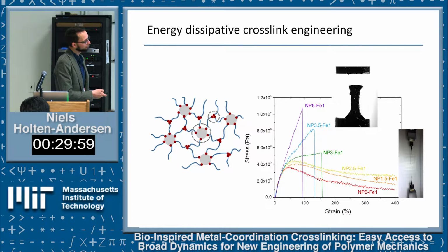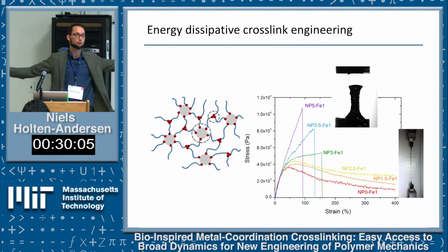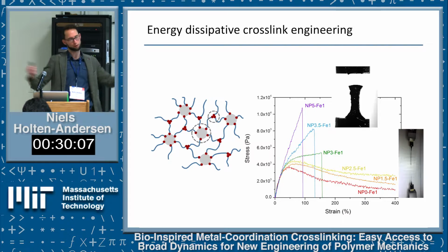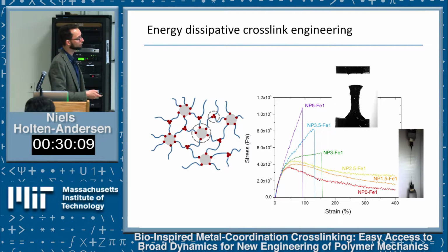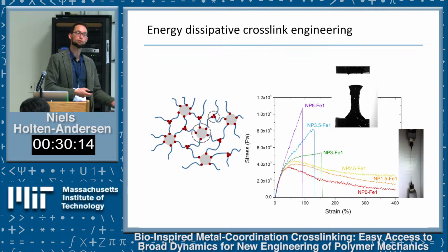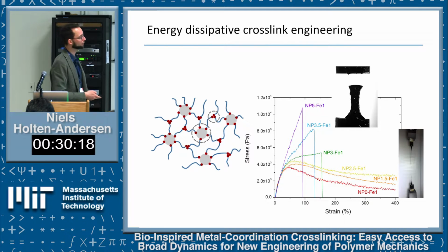This pure metal ion cross-linked material, the red one, behaves like a very viscoelastic, silly putty-like material. If you pull it fast, it can carry some stress, but if you pull it slow, it won't carry much stress. As you add more and more nanoparticles, the gels become more solid-like and ultimately almost brittle. They will actually snap if you pull them fast enough.